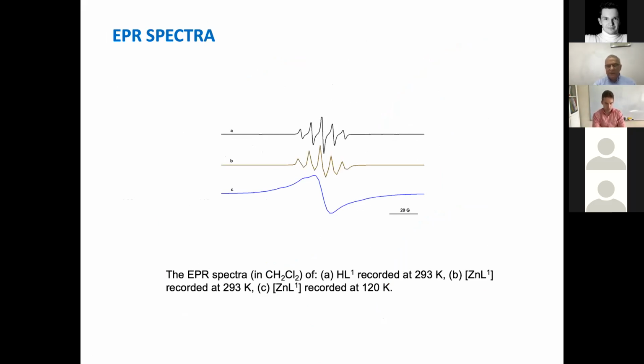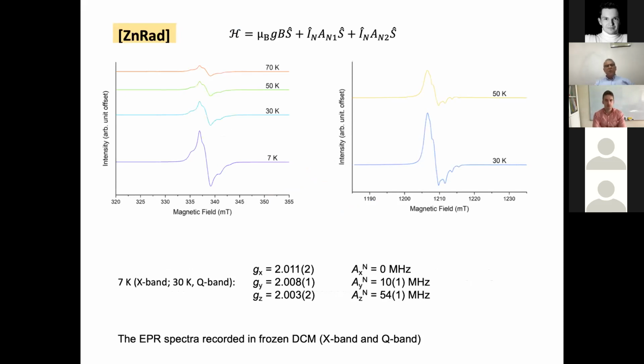Because we have this plateau I mentioned before, it can be interesting to investigate the EPR spectra with a final aim to detect whether or not our compounds can be used as qubits. First of all, for the zinc radical derivative, since zinc is diamagnetic, we will observe on all the temperature range only the signature of the radical. We also can observe that the local symmetry for this radical is rhombic. The measurements have been done both in X and Q band.